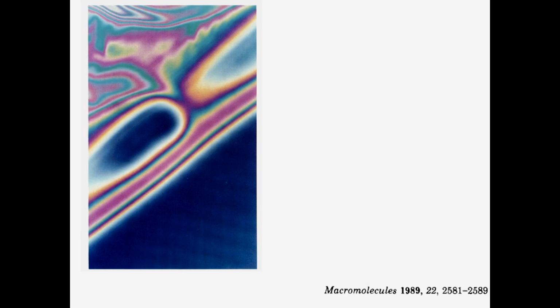because you get multiple reflections off the surface and the path length is large. So I can take a copolymer film and cast a film on a surface, and this happens to be a disordered film, and now I'm going to expose the film to trifluoroacetic acid, or if this happens to be a phase-separated copolymer, I'm going to heat it, and then all of a sudden you no longer have these nice gradual changes in color, which tells you the film thickness changes gradually, but rather you start to see these very discrete changes in color. You have step changes in color. And each of these step changes in color corresponds to one period or one pitch of the copolymer.